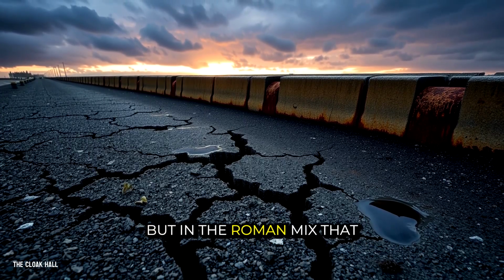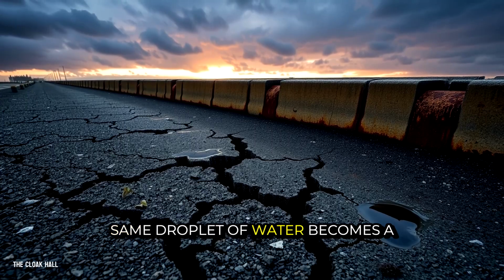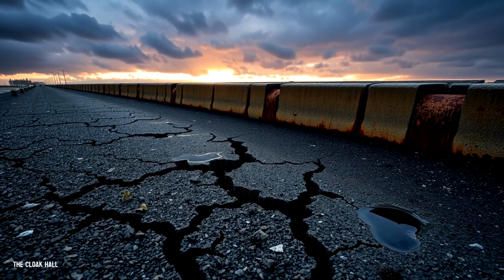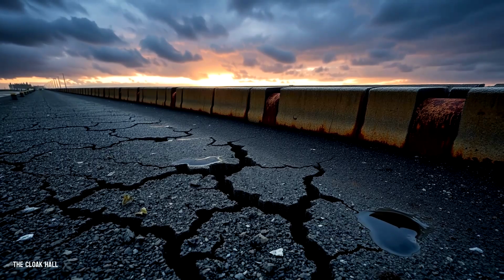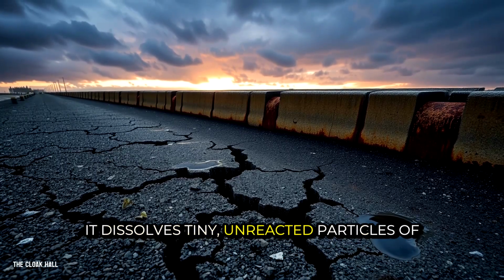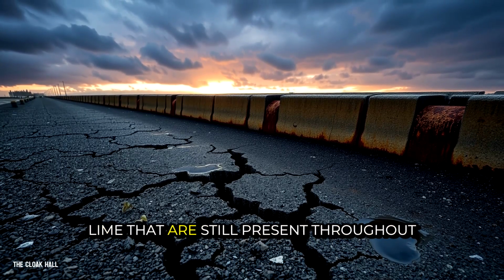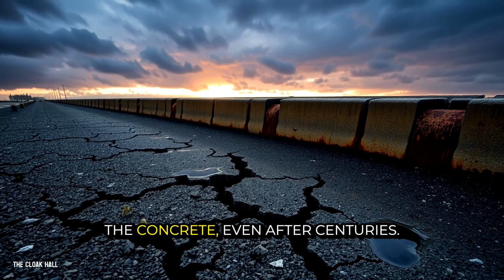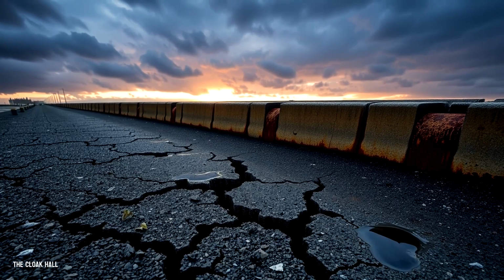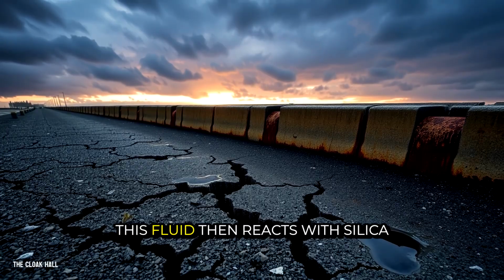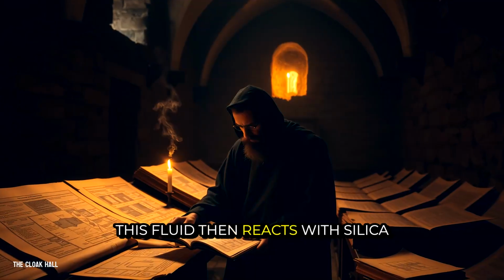But in the Roman mix, that same droplet of water becomes a healing agent. As it travels into the crack, it dissolves tiny, unreacted particles of lime that are still present throughout the concrete, even after centuries. This creates a saturated solution, a kind of mineral-rich fluid.